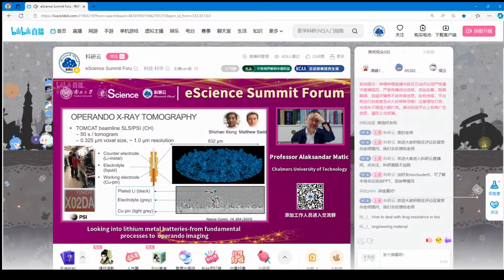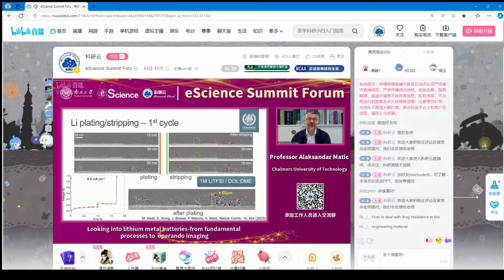So here's how actually an operando experiment looks. So you see down to the left where we have the voltage profile. So we start our deposition, we have the nucleation peak, and then we start to take images when the growth proceeds. And then we switch the current and we do the stripping experiment. So in the beginning, we don't observe anything because the deposition is very close to the surface. We cannot resolve this, but after a while, we clearly see the growth of lithium on top of the copper.